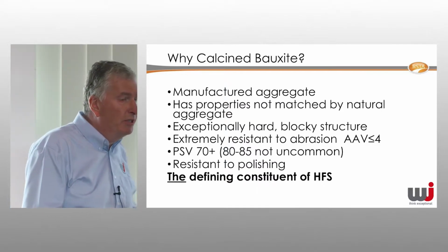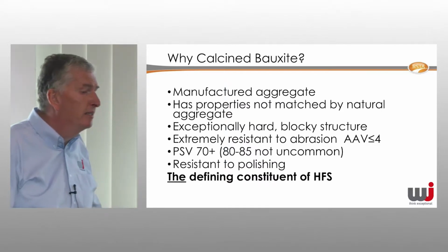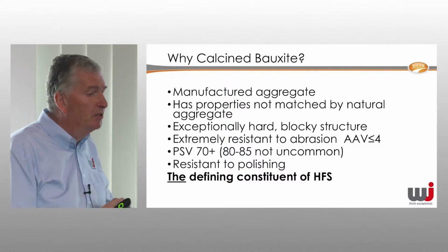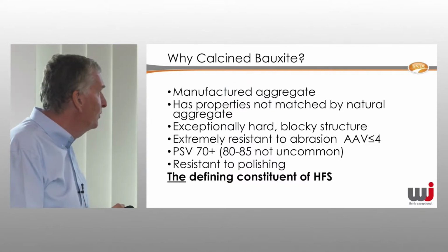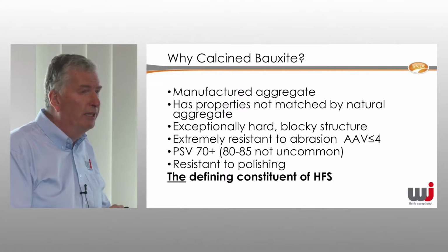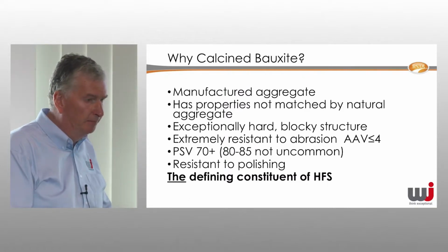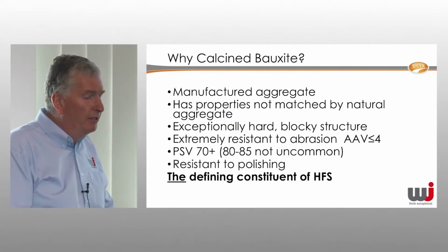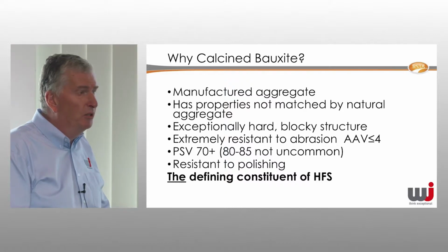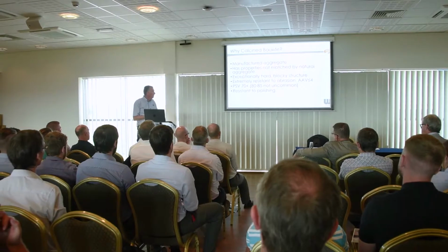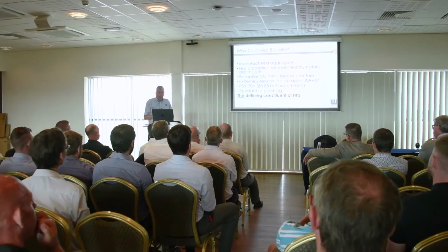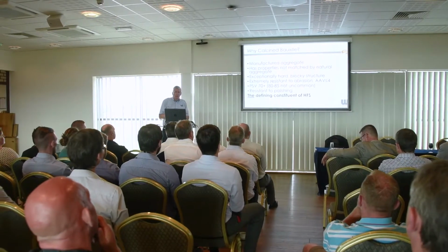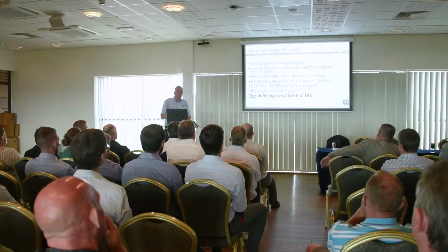In terms of the skid resistance, the PSV, the specification says 70 plus, but 80 to 85 is not uncommon and is the norm really in these sorts of products. Highly resistant to polishing. It really doesn't polish, and because of that hardness, there is no appreciable polishing that occurs with calcined bauxite. And it is the defining constituent of high friction surfacing. If it's not got calcined bauxite in it, it's not a high friction surfacing.